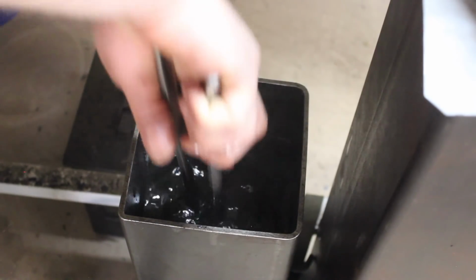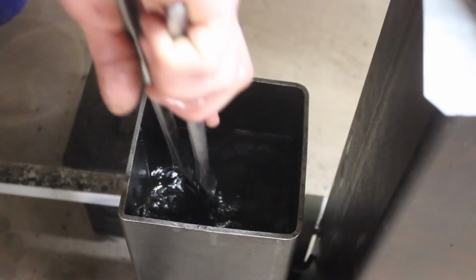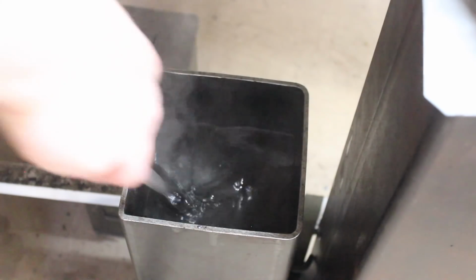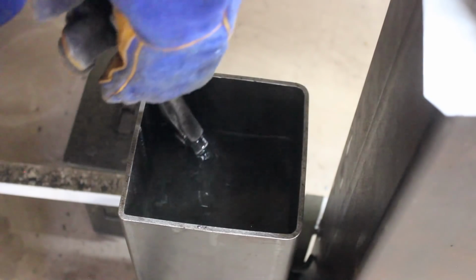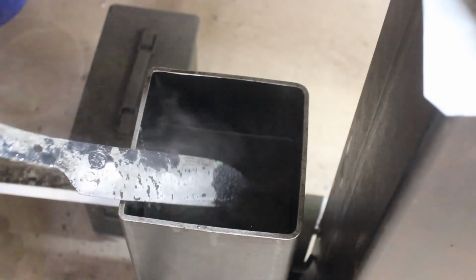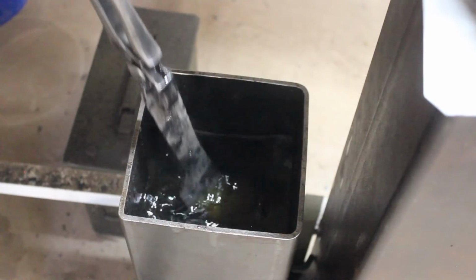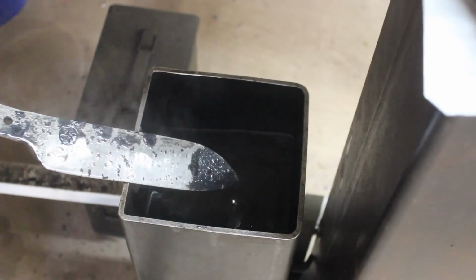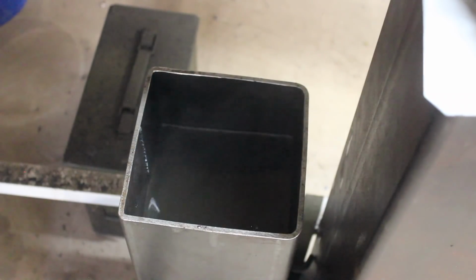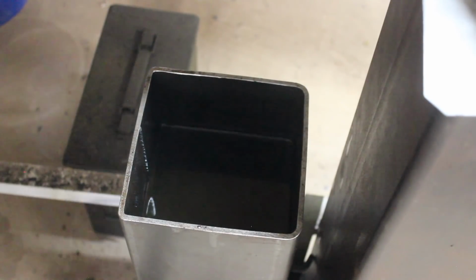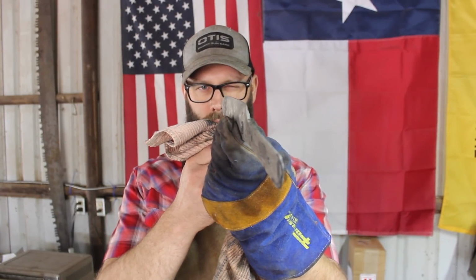If we've done everything else properly up to this point, it is in the hardest state possible for this steel, but it's too hard to make a good knife. And the reason is, when it's too hard, it doesn't have the strength that it needs. And I'm not just talking about the blade overall, which is true as well, but at the micro level on that very tiny microscopic edge, it needs to have a level of toughness, because if you think about it, the pressures that are being exerted on that steel per square inch at that microscopic level are tremendous. So it needs to have a level of toughness as to prevent it from crumbling, cracking, or breaking at the microscopic level, which would of course lead to a dull and not very useful edge.